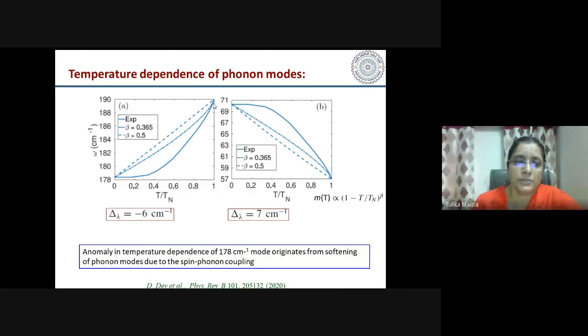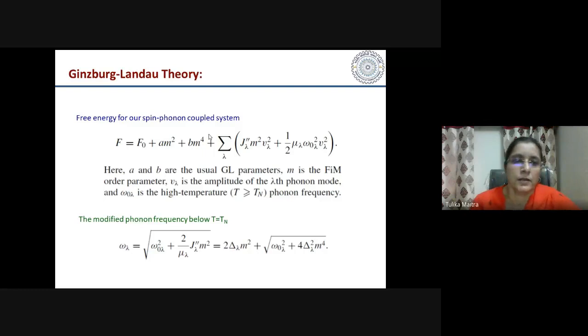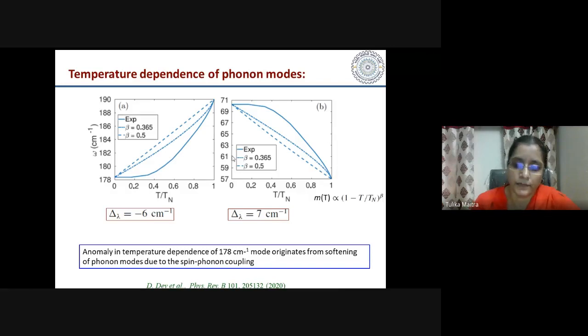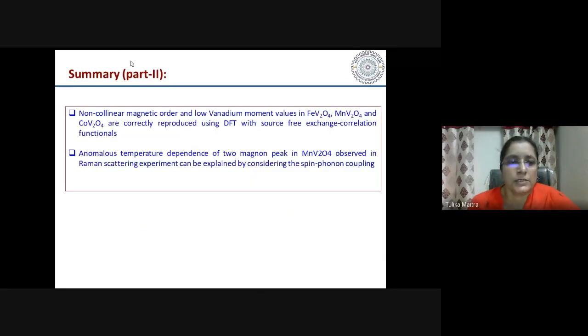Okay. So this anomalous behavior can thus be explained by considering the softening of phonon modes due to spin phonon coupling in this system. Okay, so these are the things one can do using DFT calculations, and further the DFT derived parameters can be used for a model, like a Ginzburg-Landau theory like model, or any other model calculation one can do to explain various finite temperature properties. Okay.